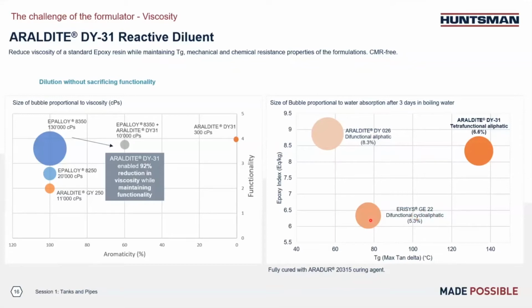And further, we put the sample into boiling water and soak for 3 days, and then we check the water absorption. So the bubble size here stands for the water absorption. You can see because of high crosslinking density, by using high functionality DY31, the water absorption rate is about 6.6%. So it's better than the 2 functionality DY026, which is at 8.3%. And Erisys GE22 is a 2 functional reactive diluent, but its cycloaliphatic structure improves the system hydrophobicity. So in this test, GE22 has a better result.